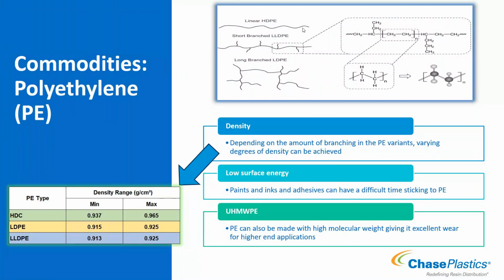And then another unique product or variant of polyethylene is what is called ultra high molecular weight polyethylene. So made with really high molecular weight, meaning the chains are very, very long. We can utilize that to make a kind of more specialty product. We would not consider it a commodity. It's a more specialized product, but that really high molecular weight allows for excellent wear performance and use in higher end applications than you would typically see standard polyethylene in.